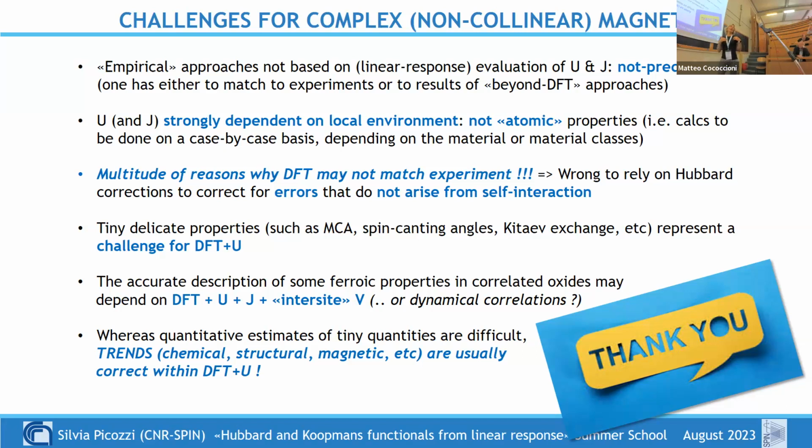But of course, if you tackle larger skyrmions, some of them are not a few units, some of them are 100, then the properties that you evaluate actually depend strongly on the lattice. So we usually always converge the spin texture as a function of the lattice size in Monte Carlo.